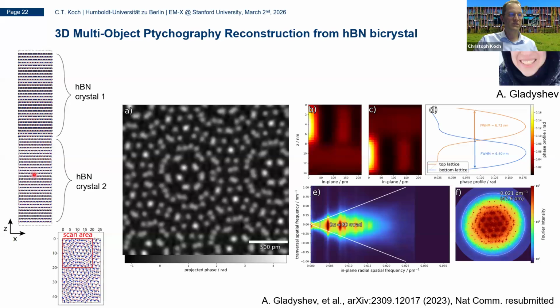So we have now these 2 crystals on top of each other. And you can see if you do the ptychographic reconstruction and you sum all the different slices together, you can see actually there is this moiré pattern. From that, you can determine the twist angle and so on. But this was a 3D reconstruction with 2 angstrom slices. So the slices had 2 angstrom thickness.